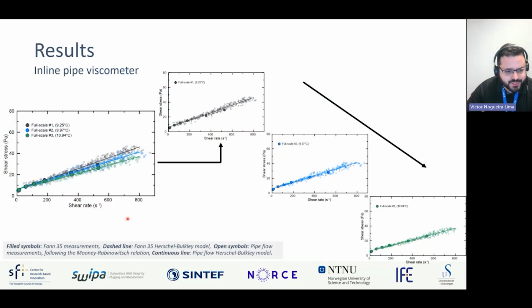So here are some of the results that we got by that time. The open symbols over here are the data that we got from the pipe viscometer measurements. You can see that we have some dispersion over here. This is because the equation that we used to get these points was a derivative equation. That's why we have these small deviations, this small noise, let's say. But if you look at the Herschel-Bulkley fit to it, that is this continuous line, you can see that you have a very good fit to the data.